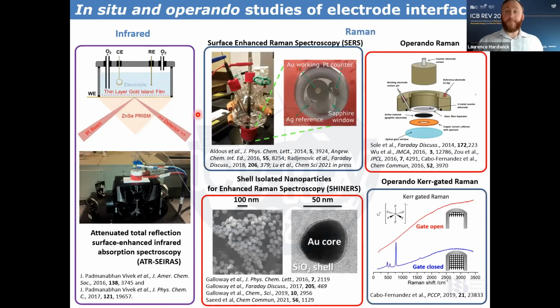We have our various flavors of Raman spectroscopy, surface enhanced Raman, where we have these bucket cells and a roughened gold electrode. You can focus a laser onto the gold electrode, then apply a potential and see what components are forming or being degraded on the electrode surface. Then we also use this technique of SHINERS, where, rather than having the plasmon on a roughened gold electrode, we have it isolated within a gold nanoparticle, and we put a silica shell around our particle. So it's isolated, and we can put these plasmonic particles onto any electrode surface and get our enhancement in this manner. We do operando Raman spectroscopy microscopy as well, using a coin cell configuration, and we look at both battery and supercapacitor systems with this technique.